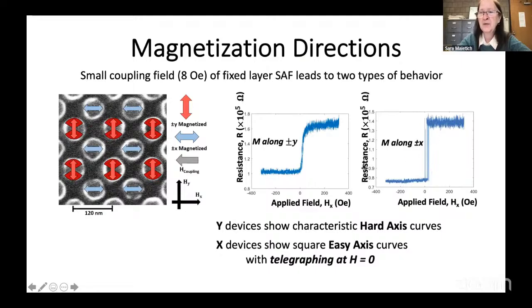And we get these S-shaped curves for all of them. At first they look similar, but then you notice that there's small differences. This one has clear telegraphing and it's sharper than this one, which is more curved. And we also notice that there's a pattern of which ones have the boxier look, the sharp jump, and which ones have more curvature. The boxier ones, we call these X devices because they're magnetized along the X direction. And these other ones have a preferential magnetization along the Y direction. If we had a Y field, they would look boxy, and these would look curved. But if we have an X field, we get this curved behavior that's consistent with what you would expect for a ferromagnet with field along a hard axis, whereas the X devices are more characteristic of a ferromagnet with a field along the easy axis.